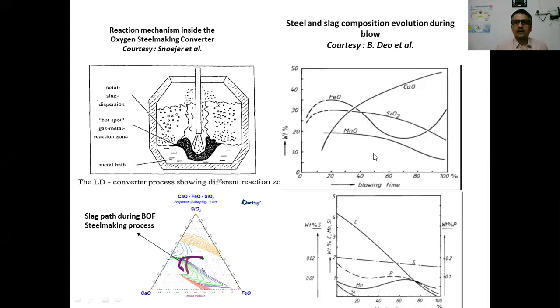Then 30–40% of the process is run at the minimum possible lance height, where the lance is able to throw the metal droplets into the already existing slag metal gas emulsion on top of it, where those metal droplets are circulating and coming back and providing the extended slag metal interfacial area, which is helping in dephosphorization. And of course, the decarburization reactions are also at the highest rate during the middle part of the blow, when the lance height is at the minimum.